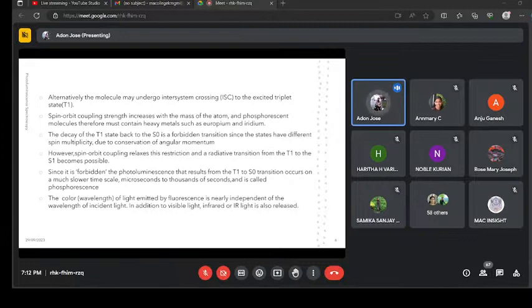Even if the spin multiplicities are different, the spin-orbit coupling relaxes this restriction and a radiative transition from T1 to S0 becomes possible. So even though it is forbidden, we can observe a transition from T1 to S0 on a much slower time scale. On that type of transition, we generally observe phosphorescence.